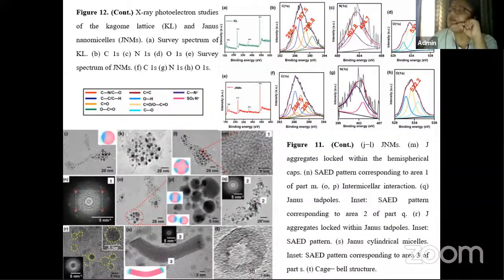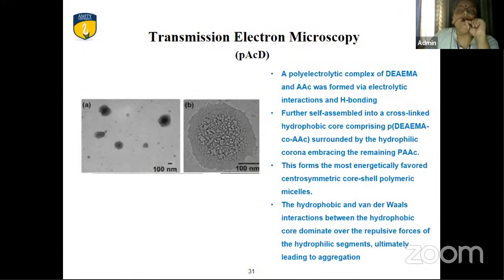Now, the question may be, why do we get Janus at higher concentration? Because GQDs are not GQDs at higher concentration, they form J aggregates. But at lower concentration, what happens? GQD remains as quantum dots, so they are properly intercalated in the polymer matrix. That's why we go for the Kagome lattice. But at higher concentration, we get the Janus nanomicelles. So this has been seen.